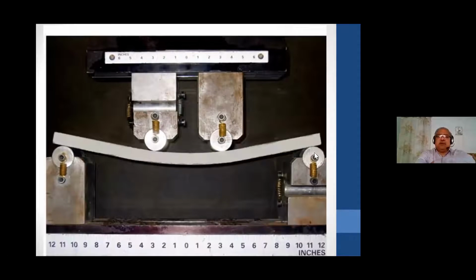You can now show the picture of the UTM at the Government College in Karad. A simple flat slab is produced out of the concrete with a nominal reinforcement. The loaders are placed on the concrete and we are now increasing the load. At this particular level, in conventional cases, you would have found that the concrete would have cracked long back, because this is not the amount of deformation or ductility of the concrete. At this level, it will make a sound and it will really break into pieces.